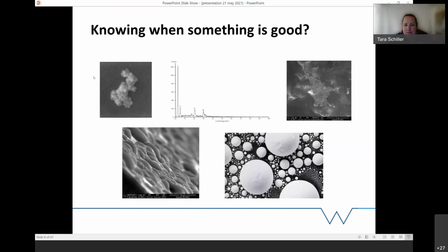So on the top left-hand side, we've got a nano bunny. This image to me in my PhD kind of made my day. It's furry, it's ugly and all that sort of thing, but it shows the extent of the coating of my polymer on my gold. Because of the surface imaging of the SEM, rather than running TEM, we could see exactly where the polymer was, rather than looking at the electron dense gold, which is what the TEM was doing and drowning out the polymer.